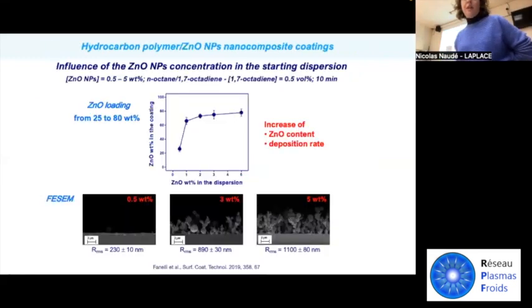We mainly focused on the composition of the dispersion, and first of all on the concentration of the zinc oxide nanoparticles in the dispersion. So as you can see here, I reported the zinc oxide loading in the coating. As you can appreciate, by increasing the zinc oxide nanoparticles concentration in the dispersion from 0.5 to 5% by weight, we obtain a zinc oxide loading in the coating ranging from 25 to 80 percent by weight.